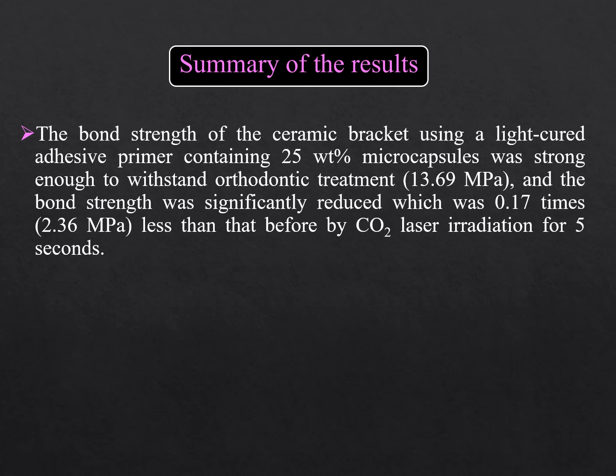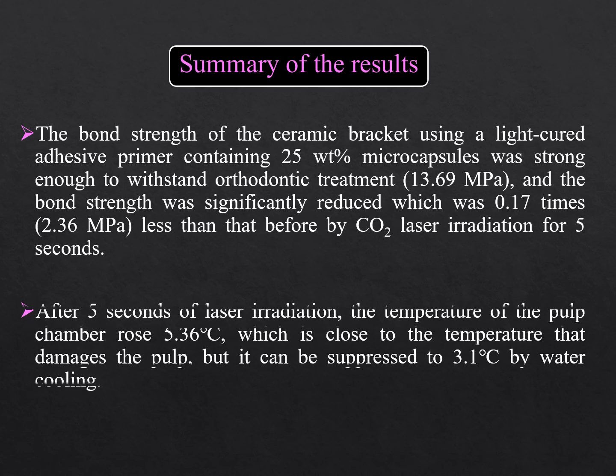The bond strength of the ceramic bracket using a light-cured adhesive primer containing 25 weight percent microcapsules was strong enough to withstand orthodontic treatment, and the bond strength was significantly reduced, to 0.17 times that before, by CO2 laser irradiation for 5 seconds. After 5 seconds of laser irradiation, the temperature of the pulp chamber rose 5.36 degrees, which is close to the temperature that damages the pulp, but it can be suppressed to 3.1 degrees by water cooling.